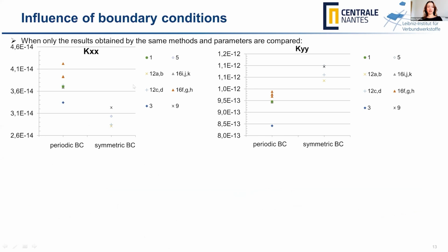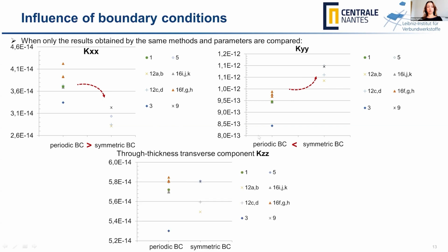Yes, thank you. So that brings us to the next point, which is the influence of the boundary conditions. It was interesting to see that when we compared the results of the same technique for periodic and symmetric boundary conditions, we had this dependence for Kx, while for Ky the tendency was the opposite. And for Kz, the out of plane value, I've just shown you that the effect of the boundaries was expected to be much smaller.